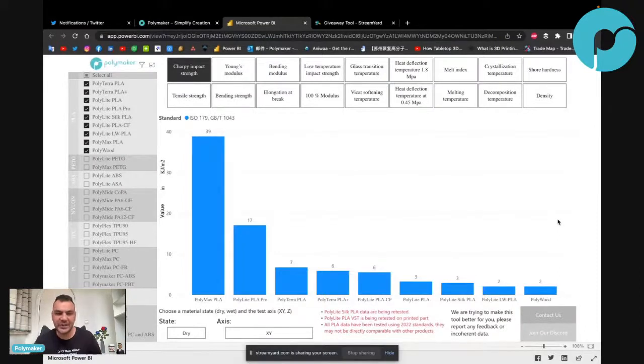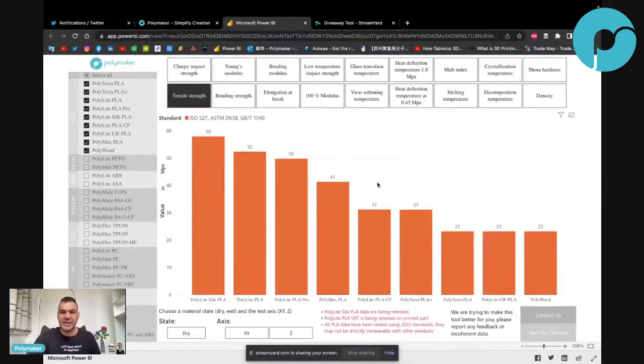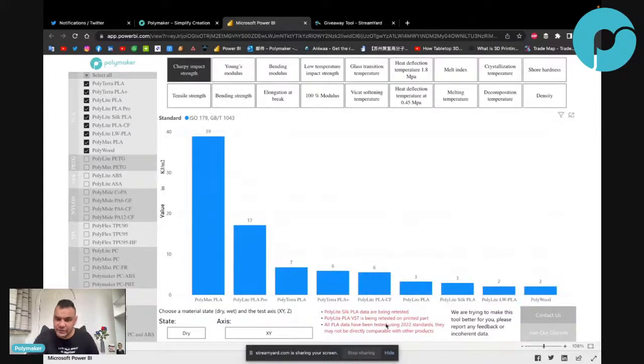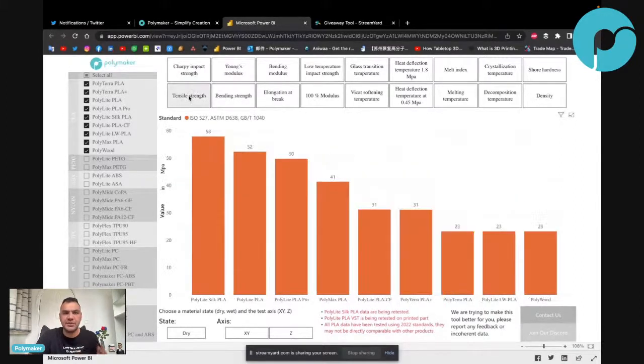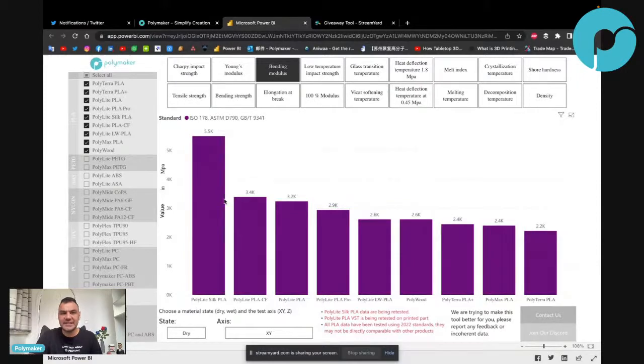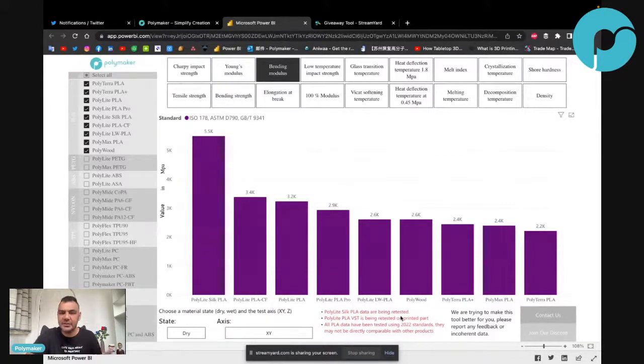Now you can see how good Polymax PLA is. How awesome is that material, right? And then tensile strength, you can have an idea. We are still revising, so you can see some data in red. In red is basically because, having so much data from 10 years of making this, sometimes it's hard to have the standard exactly the same. So, for example, for Polylite Silk PLA, we noticed that the data that we have are a little bit strange. If you check the tensile strength, the Polylite Silk PLA is the highest one, and I think the bending modulus of the Silk PLA is also extremely high. So this is data that is strange for us, so we are retesting it. That's why Polylite Silk PLA data are being retested.